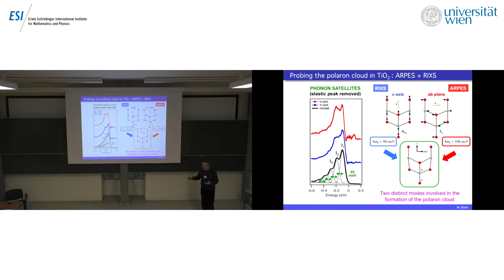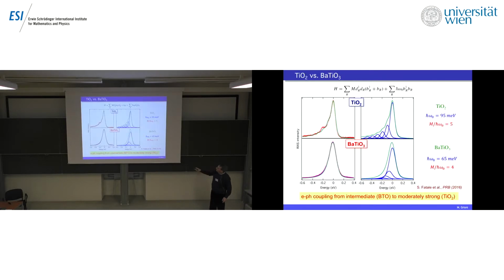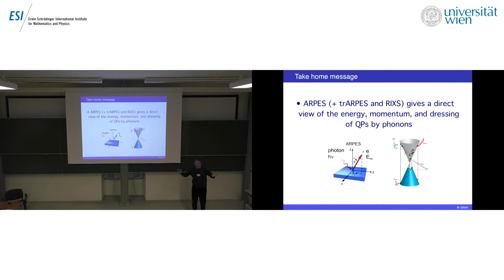So the message is that actually in this polaronic cloud, it's not just one phonon. There are at least two different phonons that contribute. And now one can fit quantitatively the spectrum and derive some parameter for the strength of the interaction. So in this, M over the energy of the phonon is something like 5 in titanium oxide, which is moderately strong interaction. And for comparison, this is another oxide, barium titanate, and it's a slightly different intensity in the tail, and this is something like 4. So this is just to tell you that doing this kind of experiments, you can also extract information about the strengths of the electron-phonon coupling. So that's all, and I thank you for your attention.